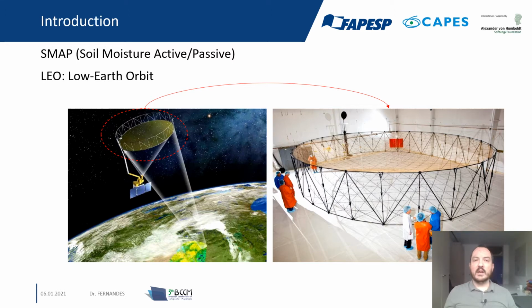In the low Earth orbit, the temperature at which these components work is at cryogenic levels, minus 150 degrees Celsius. And there is also the possibility of micrometeoroids that travel at a velocity of 10 kilometers per second. So if these micrometeoroids hit the component structure, they would cause some damage, especially traveling at such high velocities. So here again we have a complex shaped composite that is subject to barely visible impact damages. So that's another thing that should be considered.